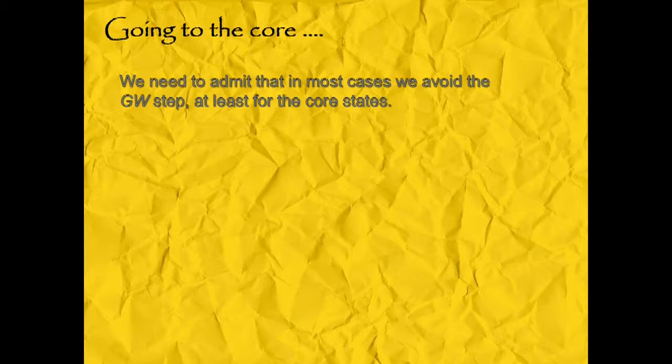Even if in GW you get relatively reliable excitation energies, even if you have a very small relative error, if you go to the core, energies are so large that the small relative error gives you a big absolute error. In that sense, it's very hard to reach the absolute onset of a core transition, and that's why we have to shift the spectrum anyway to the experimental spectrum, and then you can leave out this cumbersome step. But sometimes we need to correct at least the conduction bands.